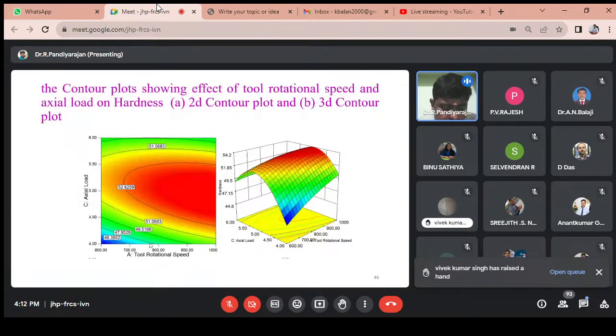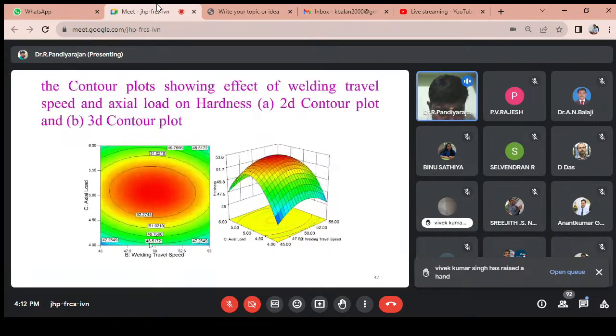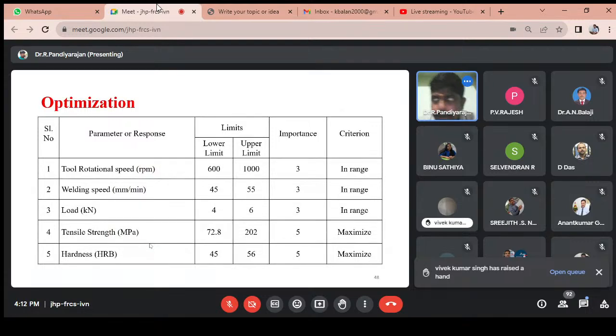This is another pair of process parameters we plotted: axial load as well as tool rotational speed, and a similar graph for axial load and welding travel speed. Those contour plots show which parameter is the most influential and which produces the highest mechanical properties. After that we set up the desirability approach, with the input parameters tool rotational speed, welding speed and axial load. We set importance to 3 and the criteria in range. The output responses, tensile strength and hardness, are set to maximize with importance 5, maintained using the desirability approach.